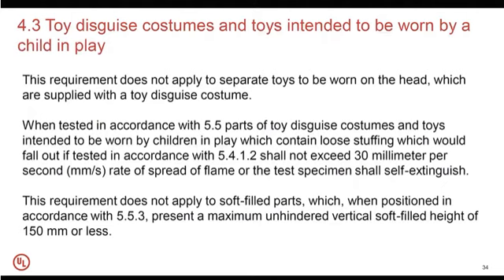So when tested in accordance with the paragraph 5.5, part of toy disguised costume and toys intended to be worn by children in play, which contain loose stuffing, which would fall out if tested in accordance with 5.4.1.2, shall not exceed 30 millimeter per second rate of spread of flame, or the test specimen shall self-extinguish. So this requirement does not apply to soft-filled parts, which, when positioned in accordance with 5.5.3, present a maximum unhindered vertical soft-filled height of 150 millimeter or less.